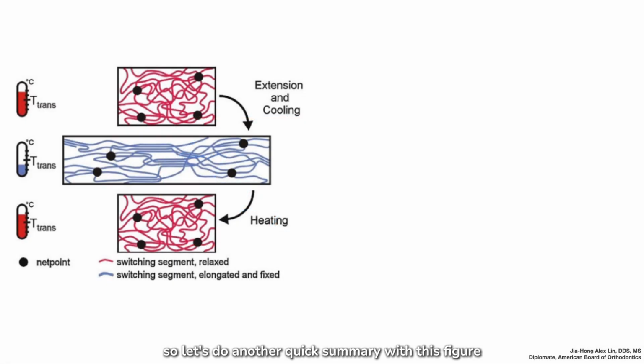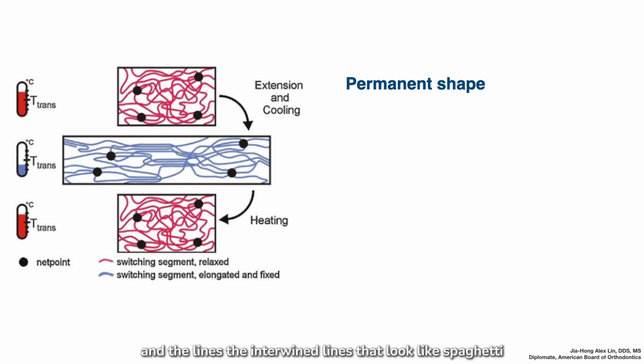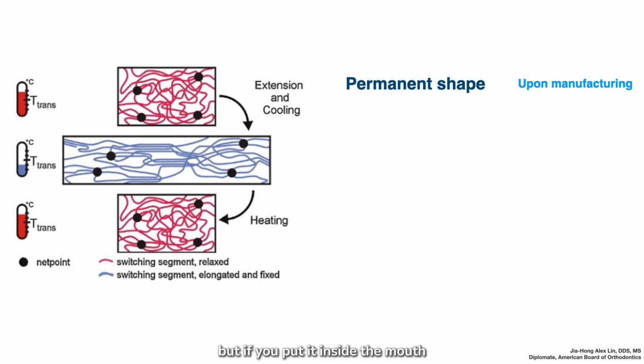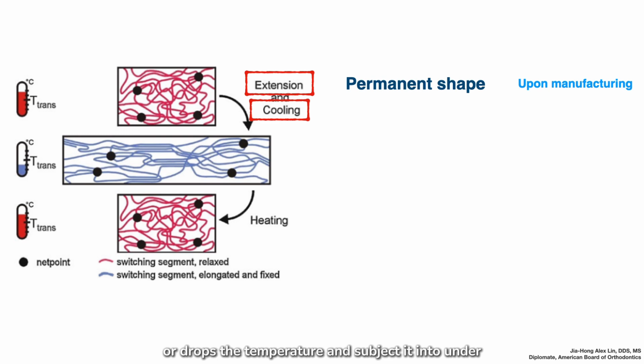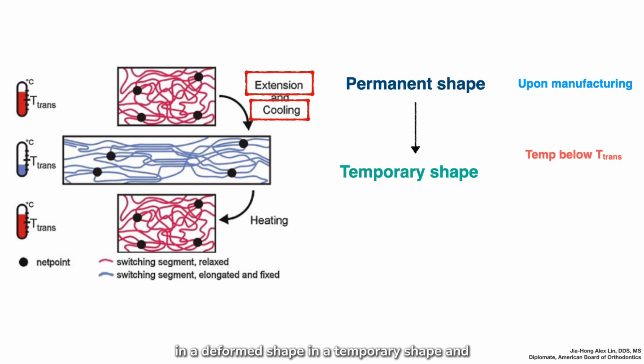So let's do another quick summary with this figure. The black dots we see here are the net points, and the intertwined lines that look like spaghetti in between are the switching segments. So when temperature is high, the spaghettis, or the switching segments, are soft, and it's the net points that determine the permanent shape. That's the shape of the aligner upon manufacturing. But if you put it inside the mouth or drop the temperature and subject it to an external force such as extension, the switching segments jump in and hold the polymer in a deformed shape, in a temporary shape.